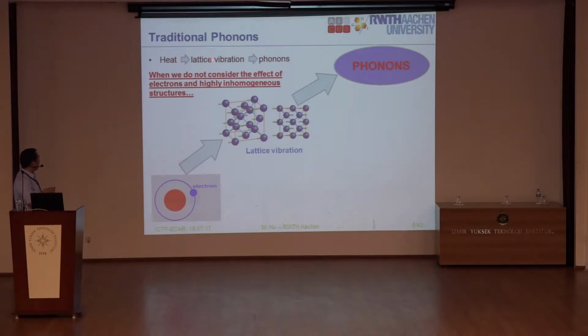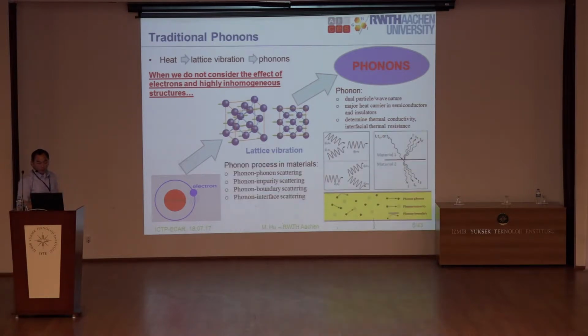So this is the traditional definition of phonons. Heat is carried by the lattice vibration, and that vibration, in the terms of physics language, we use phonons to describe this phenomenon. And then you have many different properties of phonons. For example, you have the basic three-phonon scattering or some other different types of three-phonon scattering. You also can consider the phonon scattering at the interface, because you have different structures, different phonon dispersion curves, and different phonon properties for different materials.